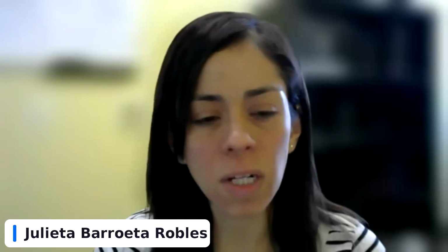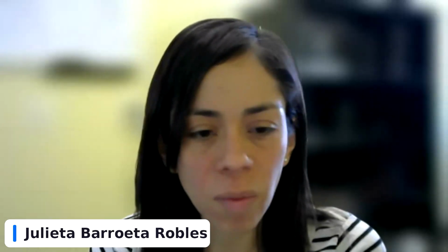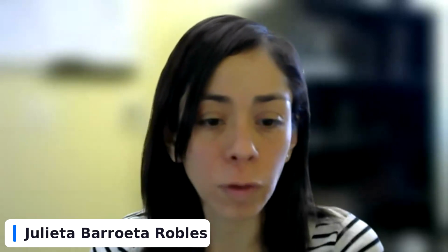Sorry, I was muted. So thank you. For the next question from Deepa Roy, is there any risk of thermo-oxidative degradation during press processing? For example, for PEEK, high processing temperature is needed. Yeah, so you do have to make sure that the time exposure of the laminate in the press forming process is not exaggerated, so not too long. But if you remember the wing leading edges and also the control surfaces of aircraft, the ribs are stamp formed in a normal environment, so not in an inert gas environment. The flanges are cleaned, and then they are well suited for a welding process. So as long as you respect the process conditions which are developed with a limited exposure at very high temperature, then the interface is fine for welding in a structural manner.